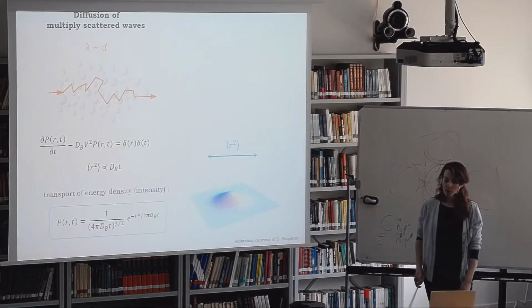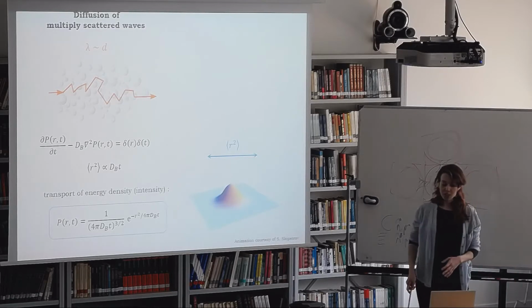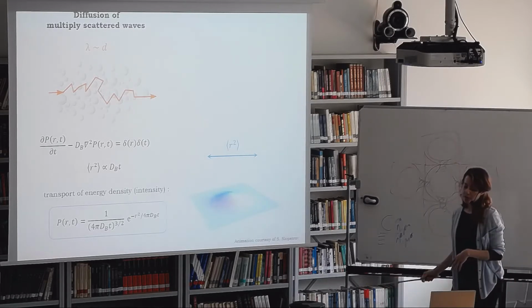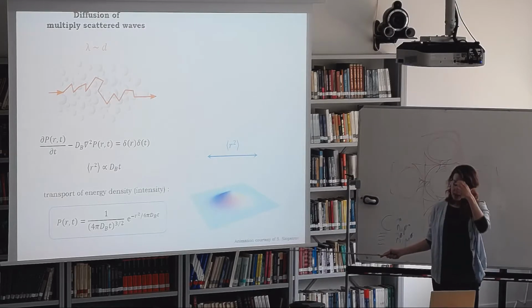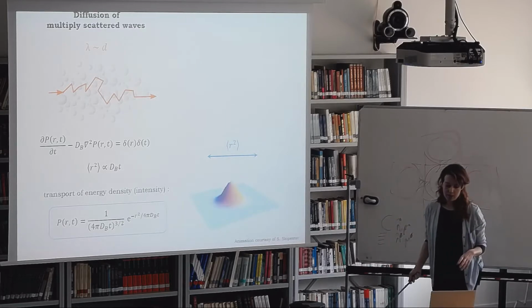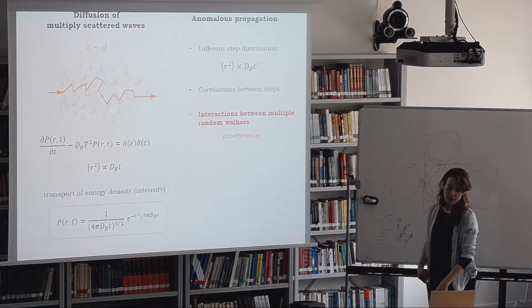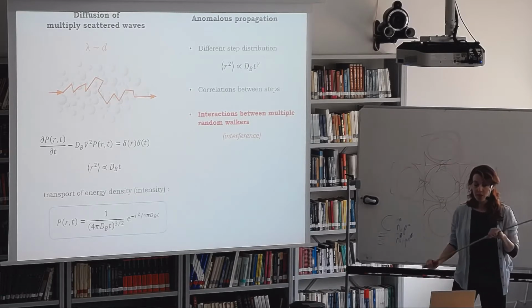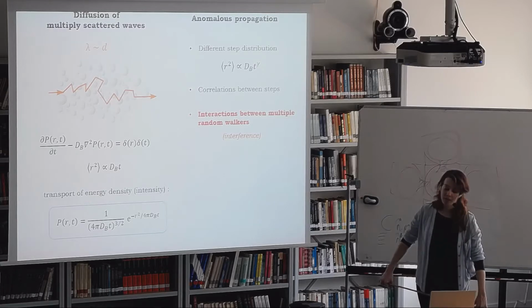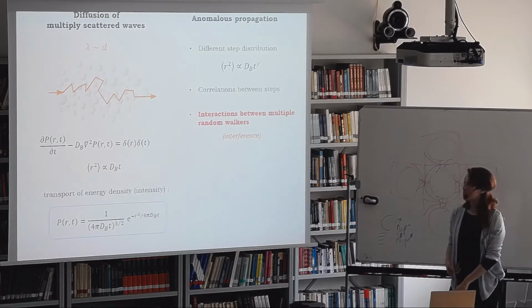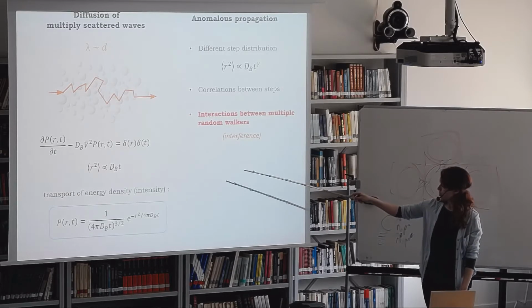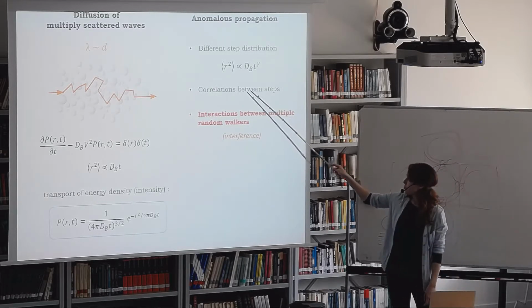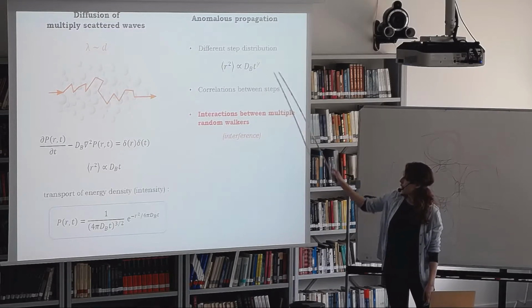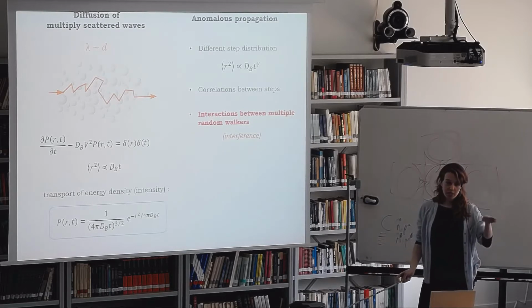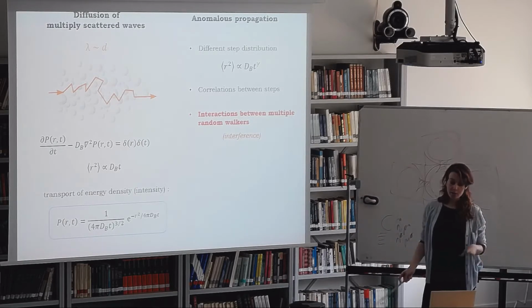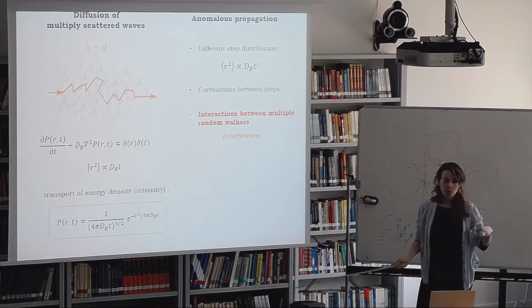So the diffusion equation works really well to describe transport in multiply scattering systems for almost all situations. For instance, it tells us the intensity will spread out on average in space and time with a Gaussian profile as such. Cases in which diffusion doesn't properly describe multiple scattering can be called anomalous propagation. We can create these situations in a couple of different ways. For instance, if we have a different step distribution than was assumed here, so the mean squared displacement has a different relationship to time, or we can have correlations between the steps of the random walker, which in this model we assume are completely uncorrelated, or we can have interactions between multiple random walkers inside the medium.